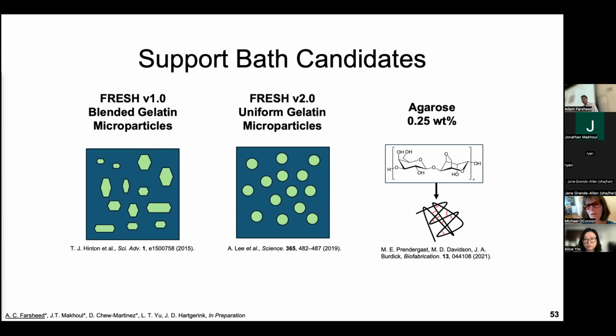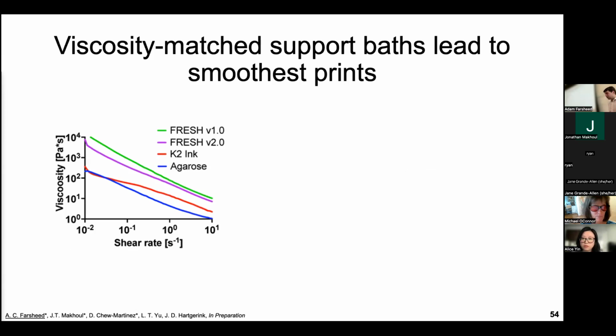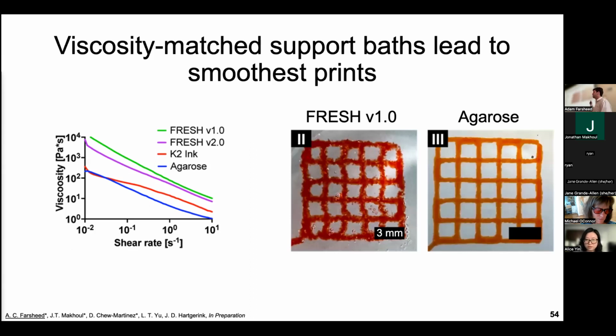And the third is Agarose, which is commonly used for 3D printing itself, actually, or in a lot of other molecular biology labs. So what I want to just quickly orient us to is we're going to, again, turn back to that rheometer from the beginning and look specifically at the viscosity of our material shown in red versus the fresh 1, fresh 2, and Agarose baths. And what we would expect and what we actually see when we go ahead and print is that the support bath that has the closest viscosity to our material leads to these nice smooth fibers. Whereas the fresh version 1, which we were hopeful would work, had these huge ridges, and when we would melt away that bath, it would actually just disintegrate our print in total.